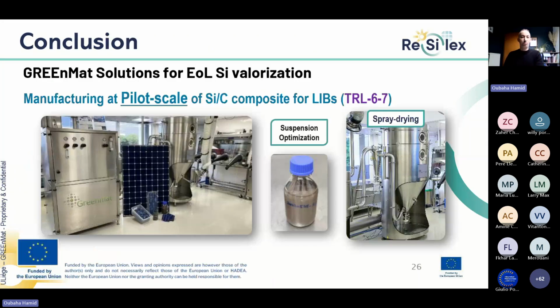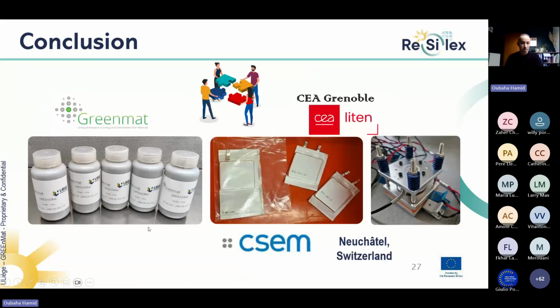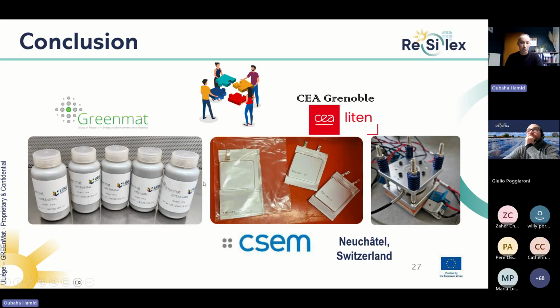So it comes to the conclusion. With the support and the funding of the European Union, we are now able to manufacture at pilot scale our silicon carbon composite, taking a step further in TRL level, reaching 6 to 7. And our composite is now tested at CEA with support from CSEM. So now I will let my colleague Willy continue and explain the achieved results in this context.